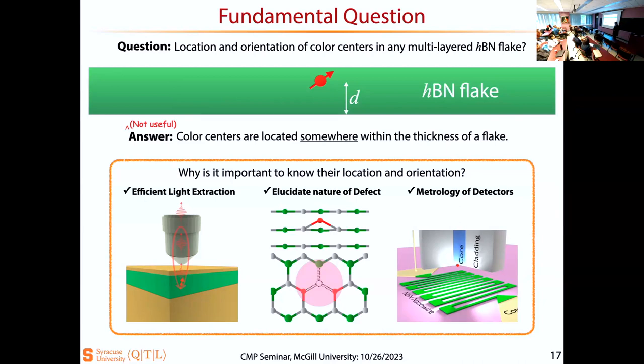Because let's say you have a truly single photon source, but in the experiment you always have an objective lens with a finite numerical aperture. And if it is a really trapped atom or ion, it decays in 4-pi. So I have to really engineer the local density of states. The photonic environment should make the light not isotropic but highly anisotropic, highly directional. Then I can really boost the collection of the single photon. And this is a very simple metal-insulator-metal, MIM, structure, which can give a directional emission.